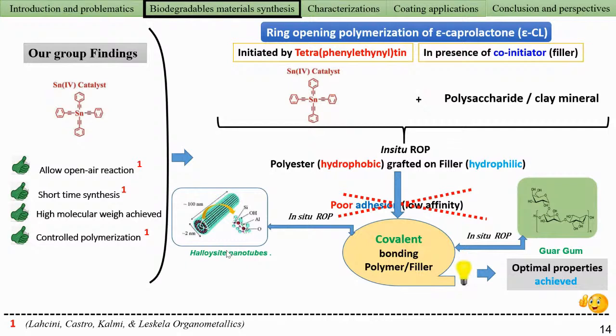But when we checked the literature, it was really hard with standard catalysts to get high molecular weight polymer grafted on the surface of polysaccharide or clay, because the more OH groups we have on the surface, the more transesterification we have, and it was reported that it's really difficult to get high molecular weight with standard catalysts. For that reason, we thought, why not use our catalyst, as we succeeded in preparing polylactide in open air without purifying the monomer. For that, we used our catalyst with a polysaccharide like guar gum and the mineral clay halloysite nanotubes.